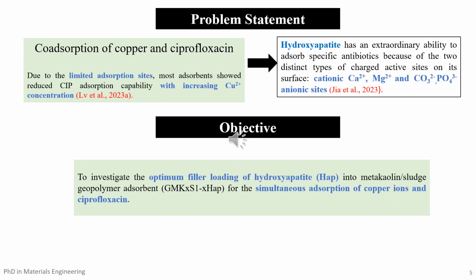So the problem statement of this study is, in the co-adsorption of copper ions and ciprofloxacin, most of the adsorbents show limited adsorption sites, especially with increasing copper concentration. Therefore, hydroxyapatite was planned to be incorporated in the geopolymer structure as it contains two distinct types of charge active sites on its surface, namely cationic calcium and magnesium, and anionic phosphate and carbonate.